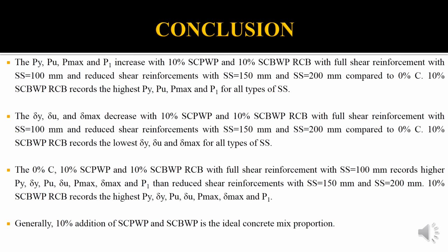The last one is the conclusion. The PY, PU, PMAX and P1 increase with 10% shredded copier waste paper and 10% shredded cardboard waste paper in reinforced concrete beams with full shear reinforcement with stirrup spacing 100 mm and reduced shear reinforcement with stirrup spacing 150 mm and 200 mm compared to 0% C. 10% shredded cardboard waste paper reinforced concrete beam records the highest PY, PU, PMAX and P1 for all types of stirrup spacing. The DY, DU and DMAX decrease with 10% shredded copier waste paper and 10% shredded cardboard waste paper in reinforced concrete beams with full shear reinforcement with stirrup spacing 100 mm and reduced shear reinforcement with stirrup spacing 150 mm and 200 mm compared to 0% C.